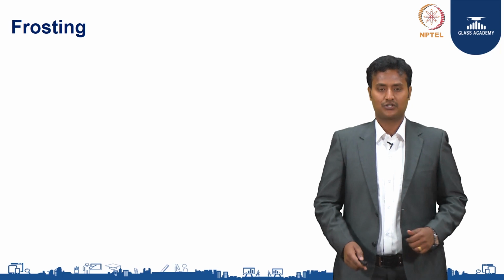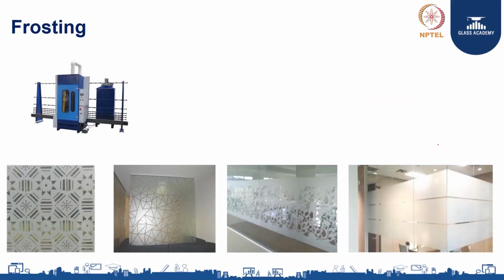Next, let's talk about frosting. Frosting is of two types: sand frosting and acid frosting. Sand frosting is done in a vertical machine where you can load the glass, and this machine has a header with a lot of orifice nozzles through which sand is pumped, thereby giving a surface roughness. Wherever you want to avoid the roughness, you can apply a polyvinyl film on the surface, so those areas are protected by the polyvinyl. Thereby you can achieve enormous designs, whatever design you want, through this masking effect with polyvinyl.